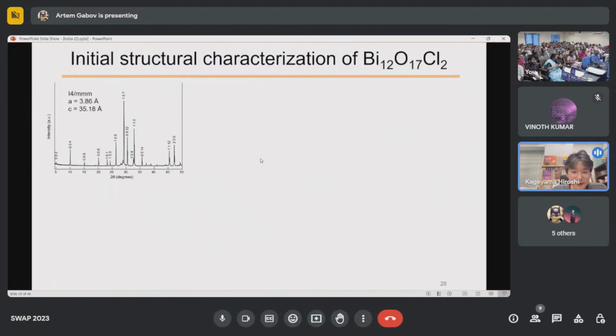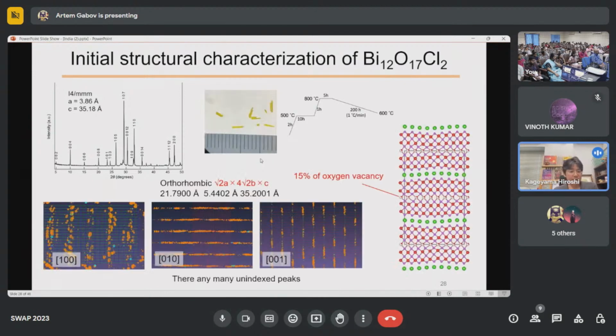Then we decided to tackle the crystal structure. As I said, this compound has a very long C-axis and is tetragonally indexed. But after single crystal or powder diffraction measurement, we found that the basic structure is okay, but actually the structure is much more complicated. For example, in this single crystal X-ray diffraction pattern, you see a lot of peaks.